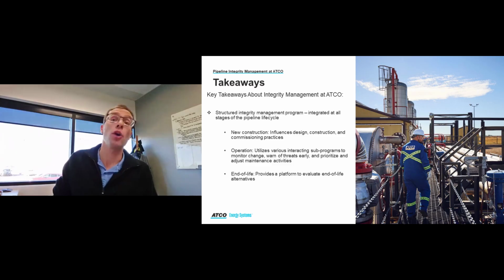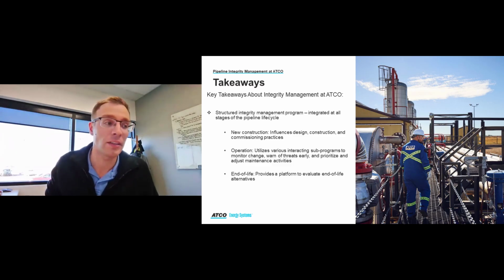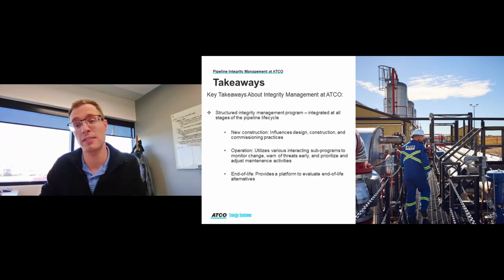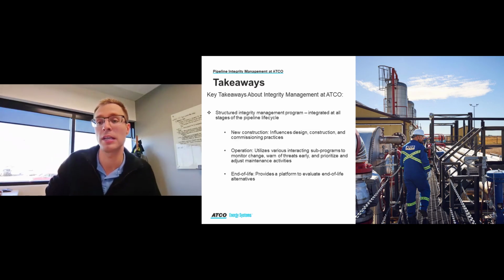distances. So high-density polyethylene, as far as I'm aware, is not suited to handle gas at transmission pressure, but it's perfectly suited to handle gas at distribution pressure, which might only be at most, or on the order of a few hundred kilopascals. So that's the primary difference. When we're dealing with the pressures that we're talking about on the transmission system, steel is by far the best option.